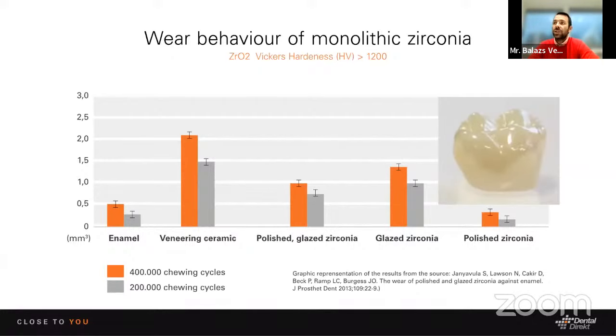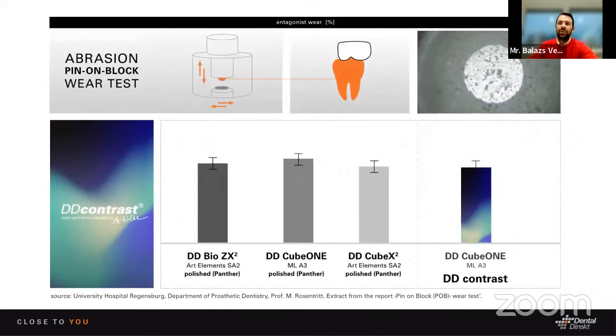Of course, for polishing, you will have a special glossy glaze on your crowns. And why I spoke before about the stain and glaze techniques, because at the end we also analyzed our contrast material, how it works, and compared it with the glazed material, how it reacts and works together with our materials. As an example, we took 3 different kinds of material from our portfolio, and we compared them with one crown which was glazed with our DD contrast material, and we saw that the polished crowns and the glazed, the Dental Direct contrast glazed crowns are on the same level.